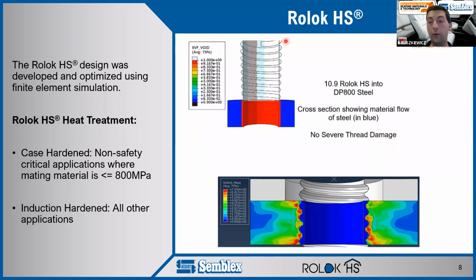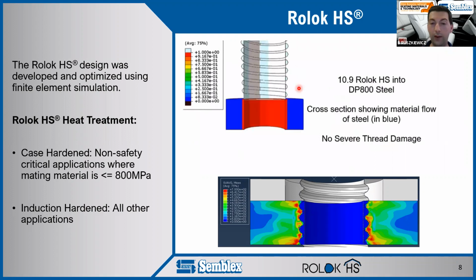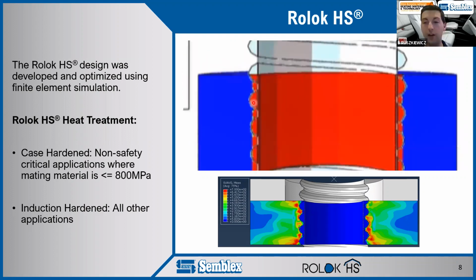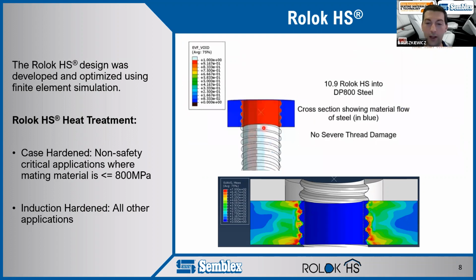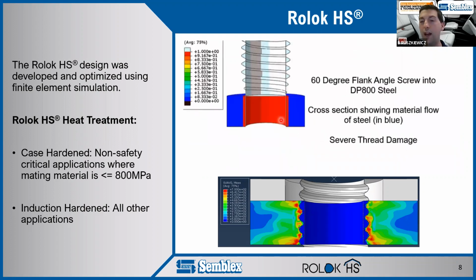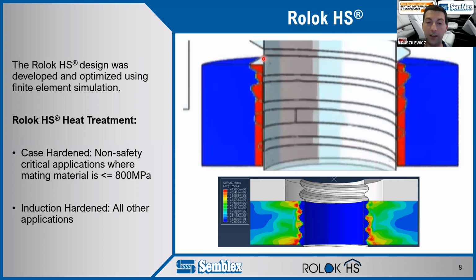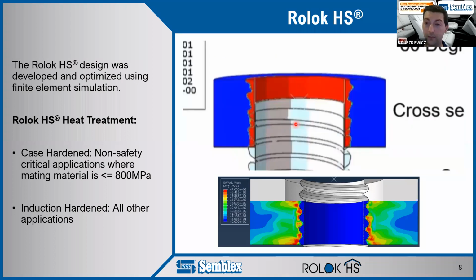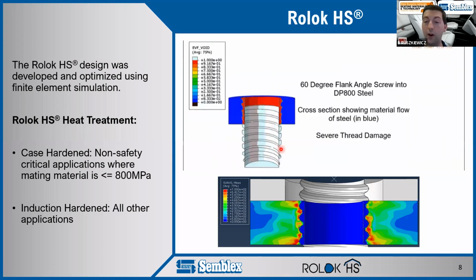It almost looks round when it's zoomed out, but when this starts to go in, you'll notice, if you look very closely, these flanks are actually compressing slightly, and they're becoming a little bit more round. But our female thread ends up looking just like the Rolok HS thread, even though we had some deformation. Very different from what we see with this traditional thread forming fastener, where the female thread at the end looks nothing like the original cross-section of this part.